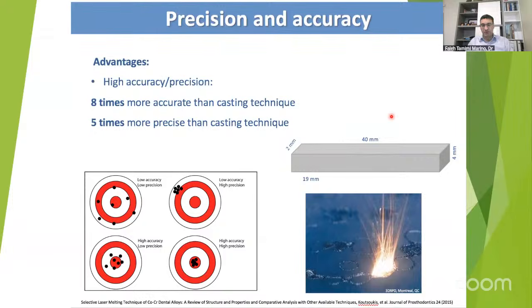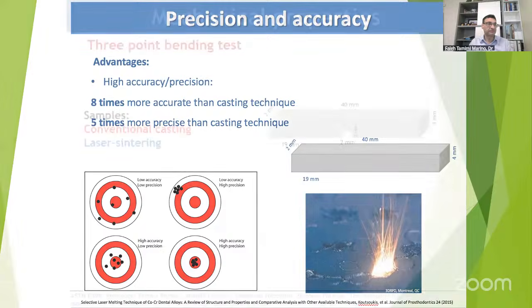Okay, so how good is this? So we did some research about this technique, and it turns out that it's 8 times more accurate than casting and 5 times more precise. Okay, so it's way better than casting in terms of precision and accuracy. So you can get very accurate frameworks. You minimize errors. So 8 times more accurate and 5 times more precise is quite a lot.